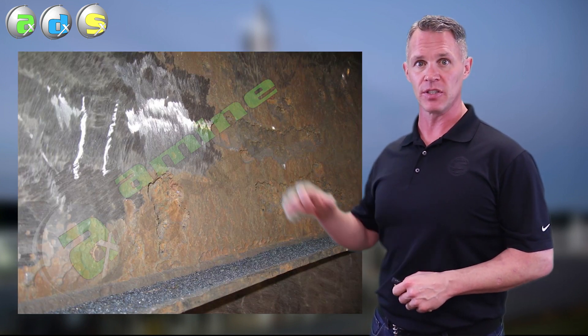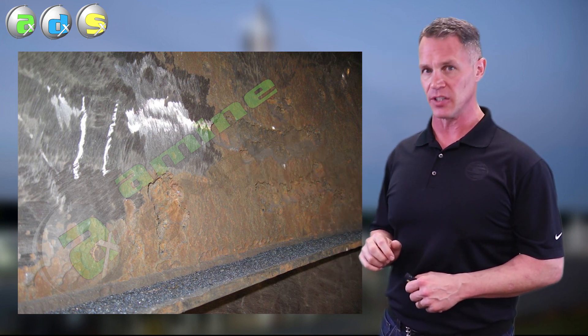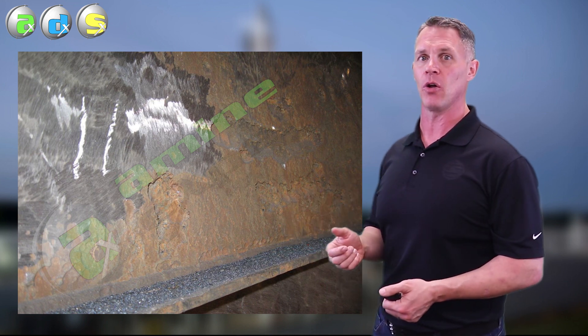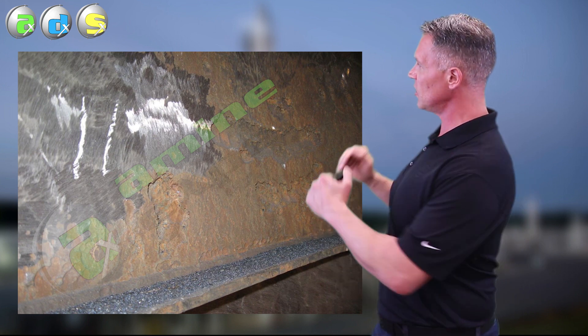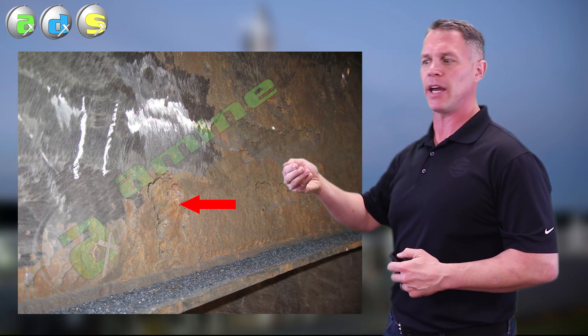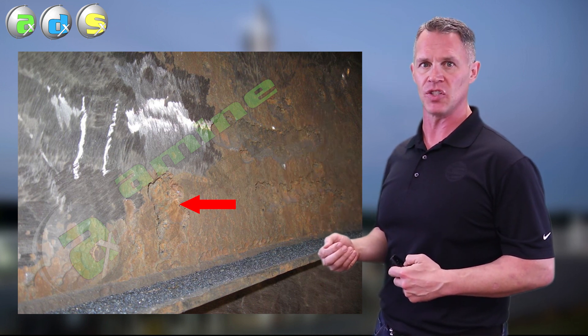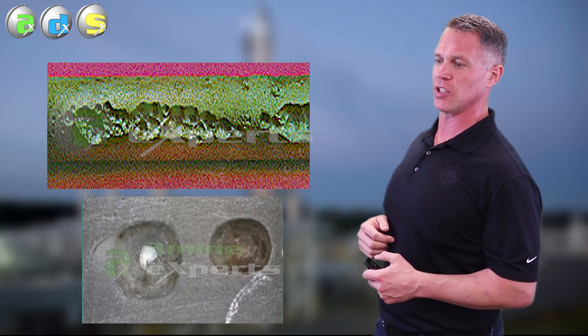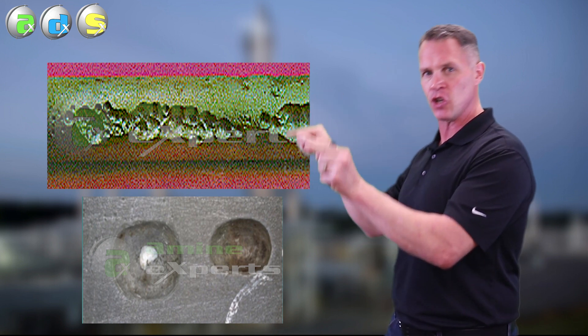Here's an example — this is an absorber with very bad corrosion inside. When we went in to inspect it after seeing severe metal thinning on our ultrasonic testing, we could see very clear pits. CO2 leaves pits — that's clear-cut evidence of CO2-related corrosion. Here's a better picture showing what we call round-bottom, very sharp-edge pits.